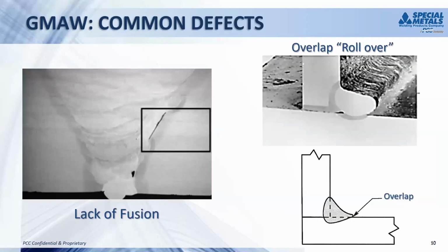Next slide. Some of the common defects that are a little more unique to gas metal arc welding with nickel alloys, as Sam mentioned, one of the big problems is lack of fusion. It's very easy to make a MIG weld that looks real pretty that you're just laying on the surface, but those surface oxides and all the other nuances of nickel welding really play against that when you get into gas metal arc welding. So you do need to be very cautious, just like with a stick weld where you're making sure you burn into that sidewall and let it fill in. You want to do the same thing with the MIG weld. Make sure you're burning in that sidewall.